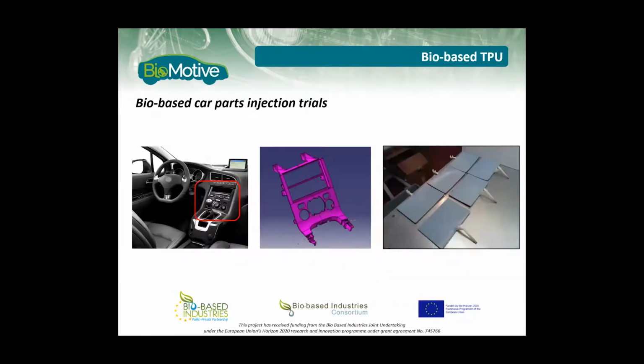This TPU has been sent to Meyer, which aims to inject such as cockpit parts, as you can see in the red square. The 3D design of the part is in the middle, but for now they tried more simpler geometries to optimize the injection conditions. So you can see on the right here that our bio TPU is able to be injected in these simpler molds. Now they are actually trying to inject it in these more complex parts.